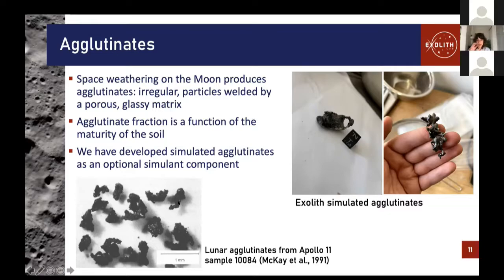So we're in the process of developing a simulated agglutinate, and we have our process down pretty well at this point. So what I've shown here on the bottom picture are some actual lunar agglutinates from an Apollo 11 Mare sample. And here on the upper right are some of these welded glassy agglutinates that we're developing. They're made of the simulant, so the glass is made from the simulant materials. They're probably a little bit on the big side compared to lunar agglutinates, so we're figuring out how to crush them and maintain some of that morphology that's so important.